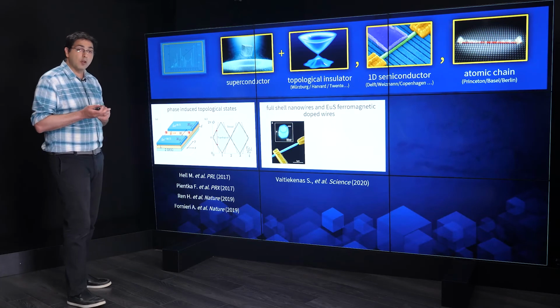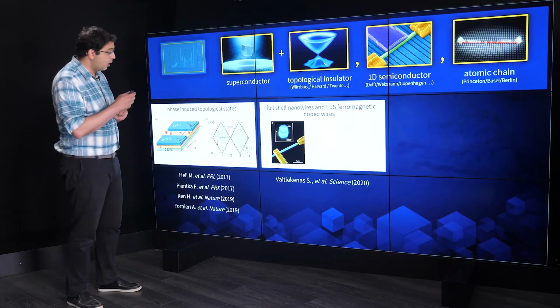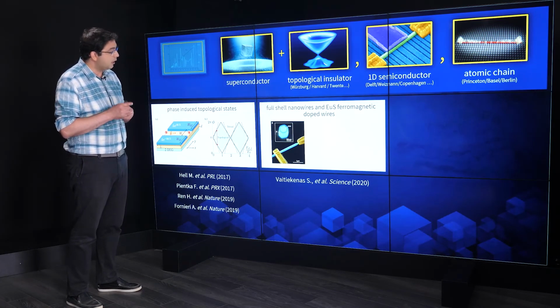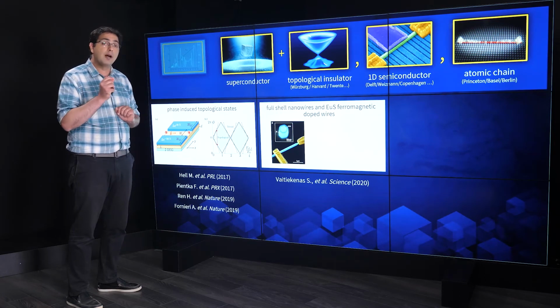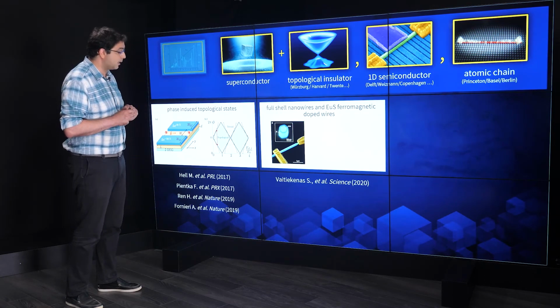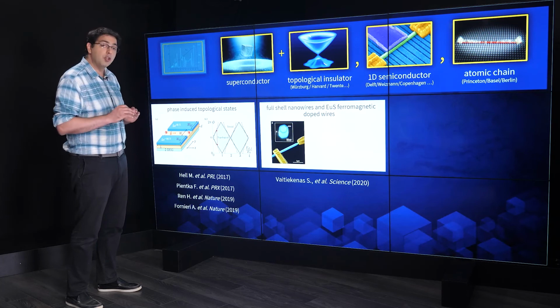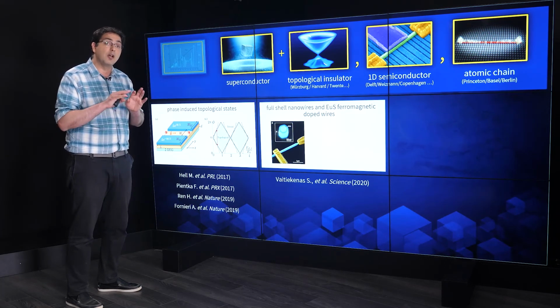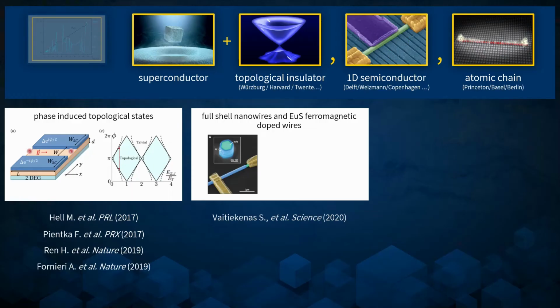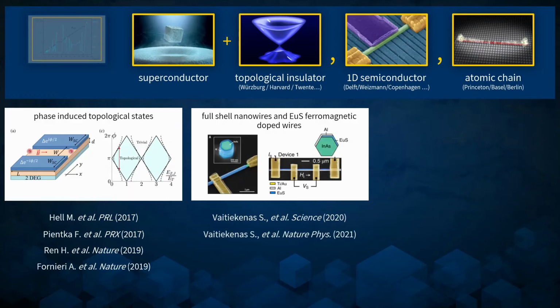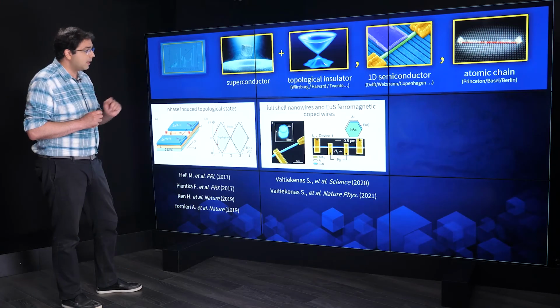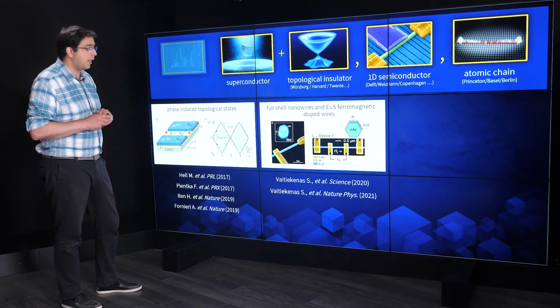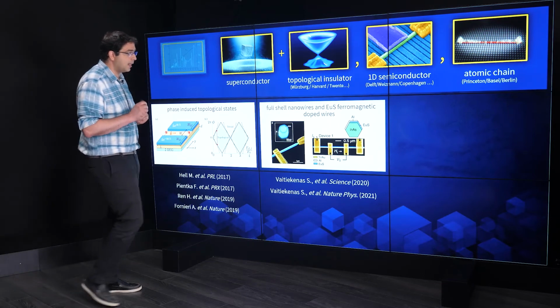Now using spectroscopy measurements, they were able to show in Copenhagen that when you introduce an odd number of vortices inside these shells, you basically again realize this zero bias peak, or Majorana zero mode physics. Another interesting experiment which comes from the same group is using this europium sulfide growth. So this is again the same as aluminum.